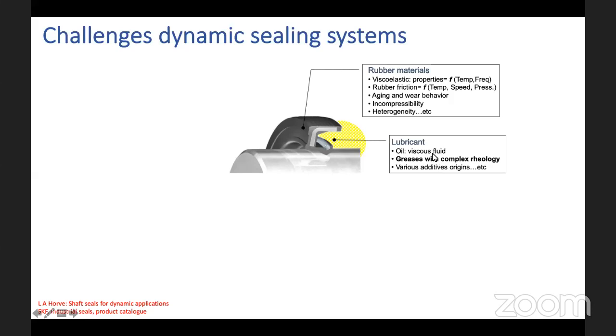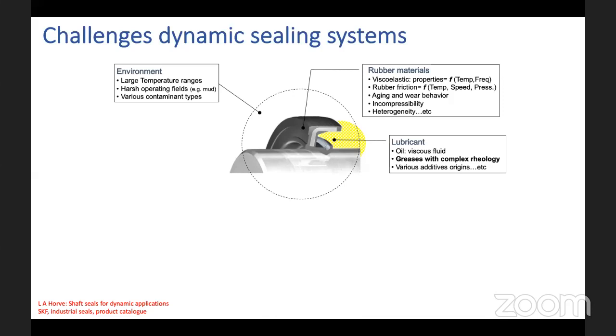In lubricants you can use grease or oil, and there are various additives in oils which have to be optimized for a particular oil and a particular sealing system. Oils should be chosen such that the rubber material doesn't get degraded and doesn't lose its elasticity. And then the environment: what temperature range are you looking at? If you want to seal at low or high temperatures, under harsh operating conditions, for example in oil and gas industries, there is demand for high temperature, high pressure sealing systems. And in the automotive sector, you need seals which can last up to 25 years. High lifetime, low friction and low wear are needed. So there are many requirements, and you have to optimize many properties like these.